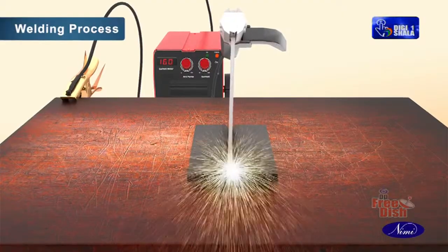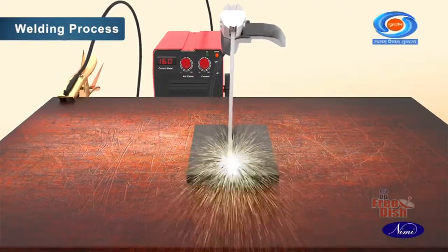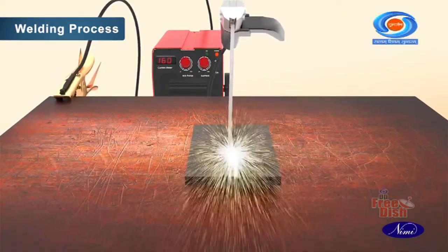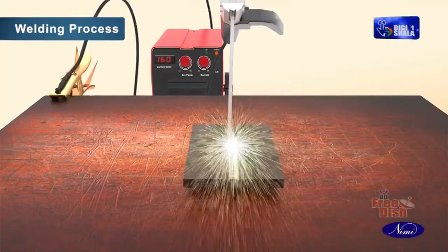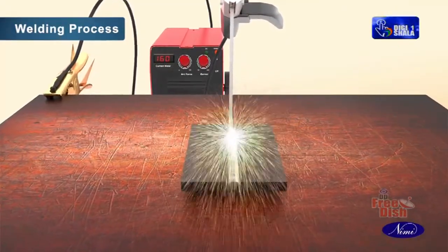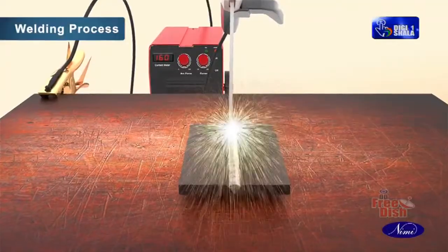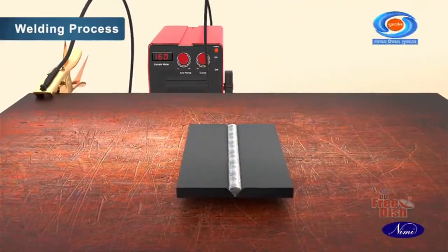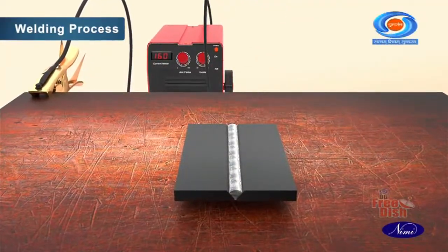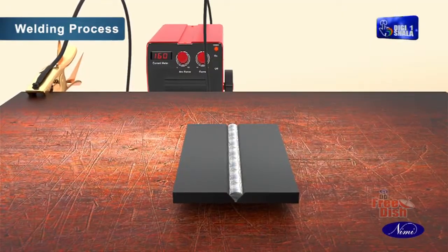Deposit the third or covering run using the same parameter and technique used for the second run. Ensure a proper reinforcement of 1 to 1.5 mm and avoid undercut. Inspect for any surface weld defect.